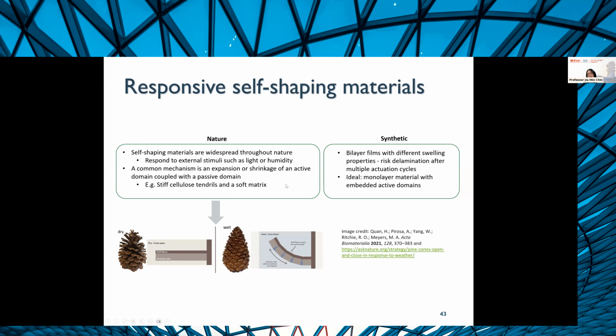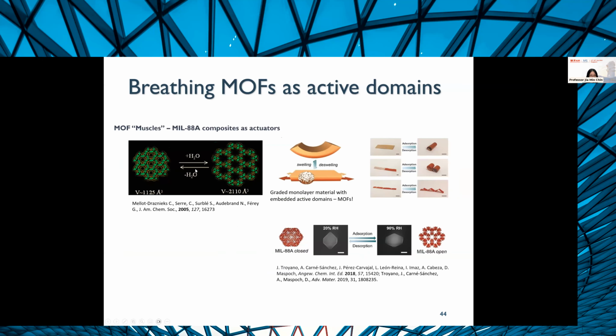So people have taken these ideas on board and used them with MOFs for responsive actuators. A classic example is MIL-88A. This MOF is chosen because it has a very large volumetric response in the presence of water. It almost doubles its volume when it takes up water. And the Maspoch group has shown a couple of examples where they disperse MIL-88A in a polymer matrix. They see that if they have a gradient in the density of the MOFs, with more MOFs at the bottom, then you have more swelling at the bottom.